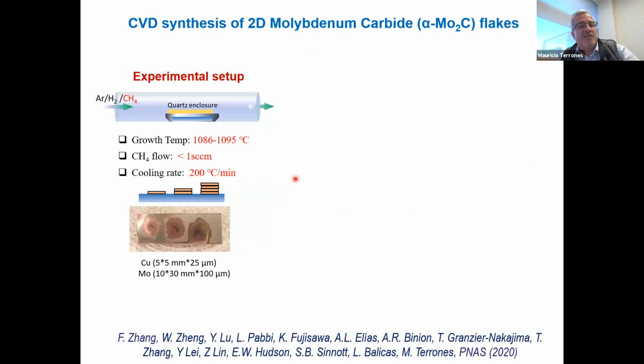So in this case, there's some paper already where they made these alpha moly carbide flakes. So it's easy to make. Basically you have a moly film and you add some copper foils as well, and then you flow methane, right? And then you can do it by stacking the moly and copper foils like this or like this.